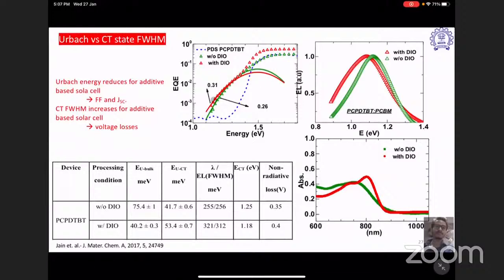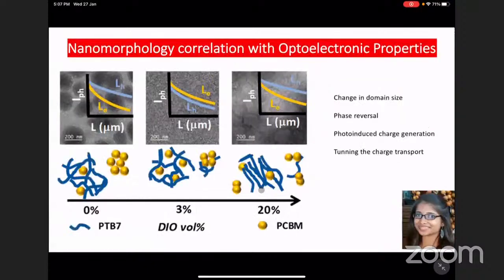And then again here, this is the photothermal deflection spectroscopy, which we got done at Cambridge. This is for the pristine films, and the photocurrent response goes beyond the absorption of the pristine films because there is a charge transfer absorption as well. And that allows us to further say that, okay, additives really help. By adding the additives, we see a slight red shift in the EL emission peak with DIO, but overall lots of gain in the fill factor and the JSC.